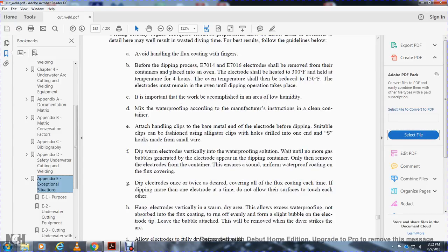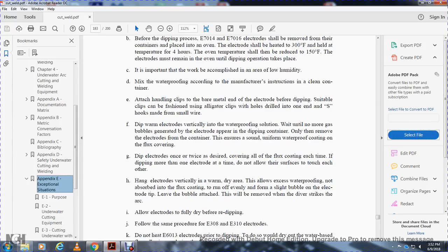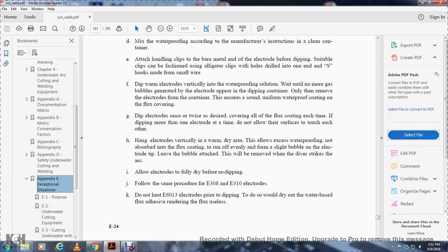It is important that the work be accomplished in an area with low humidity. Mix the waterproofing according to the manufacturer's instructions in a clean container. Attach a handling clip to the bare metal end of the electrode before dipping. A suitable clip can be fashioned using an alligator clip, or a hole drilled at one end with an S-hook made from small wire. Dip the electrodes vertically in the waterproofing solution. Wait until no more gas bubbles appear in the dipping container, then slowly remove the electrode from the container. This ensures a sound, uniform waterproof coating over the flux covering.